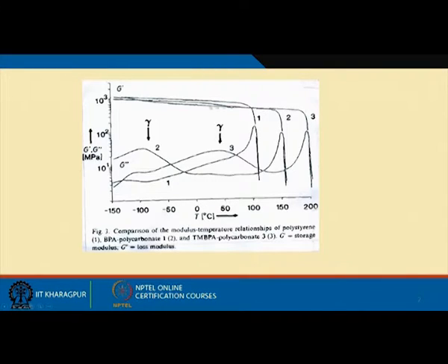So, this is segmental motion, where a big segment has been freed from rigidity and has started to have motions. That is the point at glass transition temperature, but much below glass transition temperature you can also have motion of 2 or 3 carbon atoms together, maybe a slight rotation around the phenyl carbonate bond. Those kinds of rotations or small motions can absorb energy. So, those are not completely rigidified at a temperature lower than glass transition temperature. They have different names for relaxation; for polycarbonates, this is called gamma relaxation.